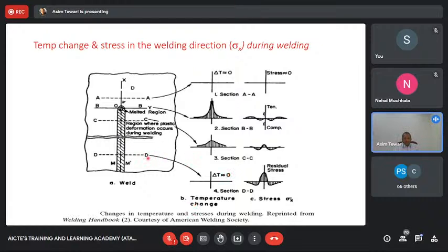And there is no temperature. It is still at room temperature, which means it has gone back to AA. So what we are doing is we are looking at AA, then we are looking at BB where the melt pool is there. We are looking at CC a little behind BB. And then we are looking at a very far away region, which is again back at room temperature. And this is how the residual stress variation has happened.